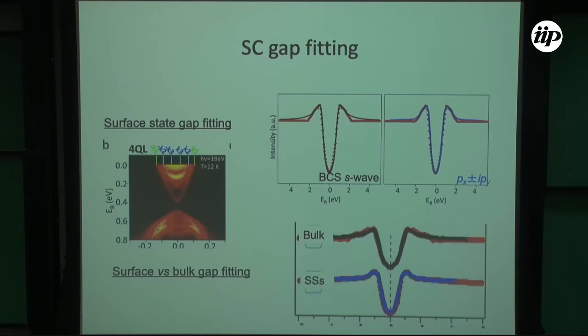Now, above TC, when you cool down, everything becomes superconducting. All bands open a superconducting gap, right? But we can also image how much gap is open in the bulk and how much in the surface. So what we can do is look at the spectral function in the bulk band and also in the surface band. The color coding is not quite right: the bulk is black, the surface is blue. If you try to fit with a BCS wave function, the bulk has a little less agreement, and on the surface, probably a little better agreement.